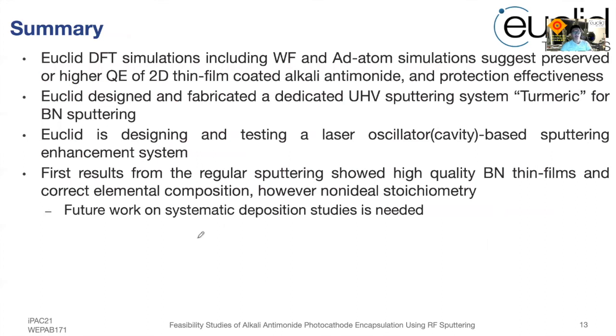As a summary, we have done DFT simulations at Euclid, including the work function and Ad-atom simulations to suggest that the 2D thin films can preserve the work function for, or even reduce the work function for alkali antimonides. And also the Ad-atom simulations have shown that the thin film can protect the substrate or the photocathode from oxidation. We have designed and fabricated a dedicated UHV sputtering system for boron nitride sputtering on photocathodes from scratch. We're designing and testing a laser oscillator or a cavity-based sputtering enhancement system.